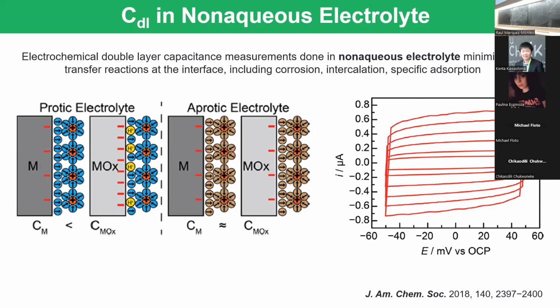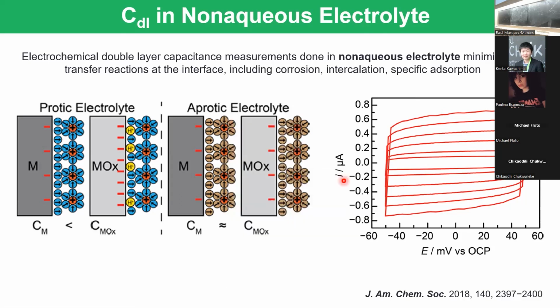So it turns out that working with organic electrolytes, like aprotic solvents, for instance potassium hexafluorophosphate in acetonitrile, works better, because if you do that, you can prevent any kind of interactions or ion transfer reactions that are not desirable. Okay, and this is the way the shape of these CV scans should look.